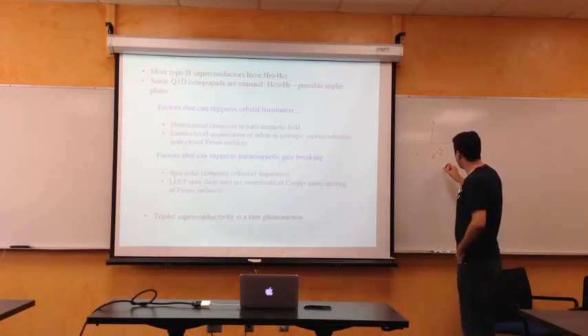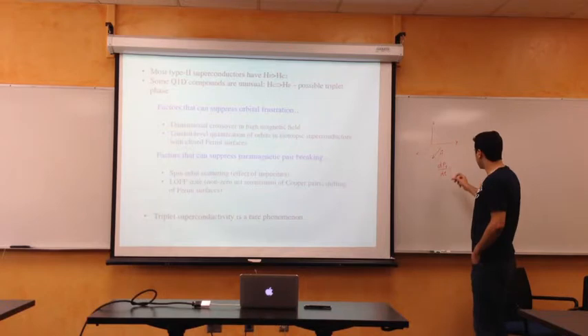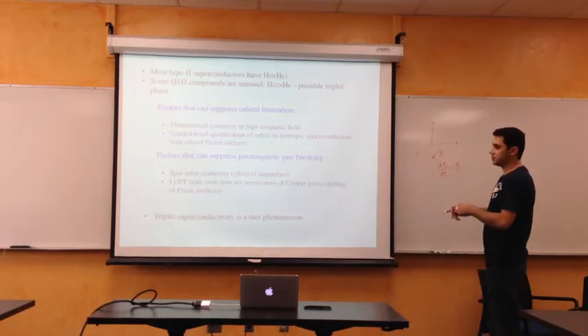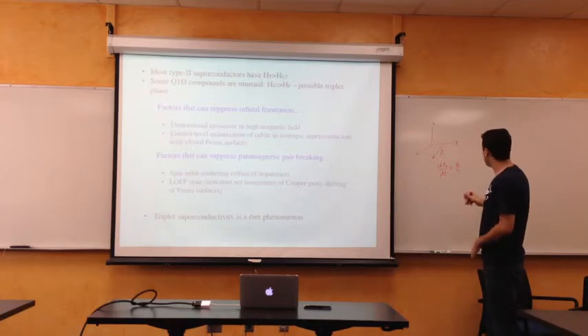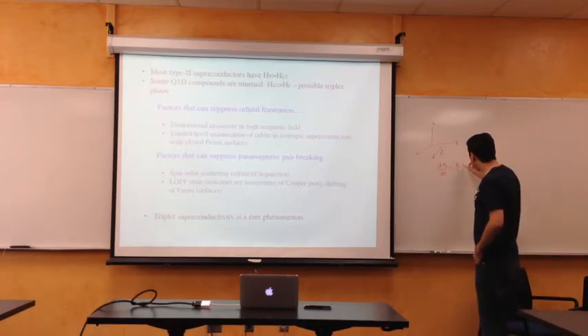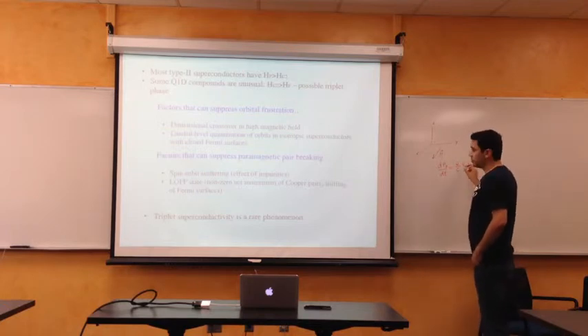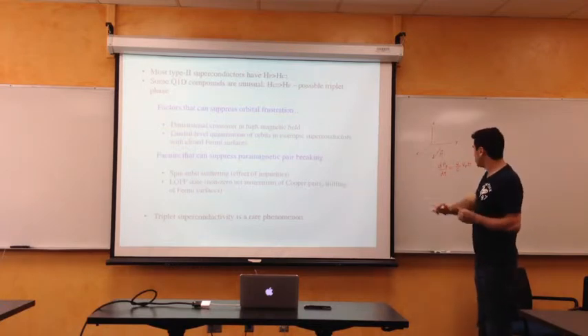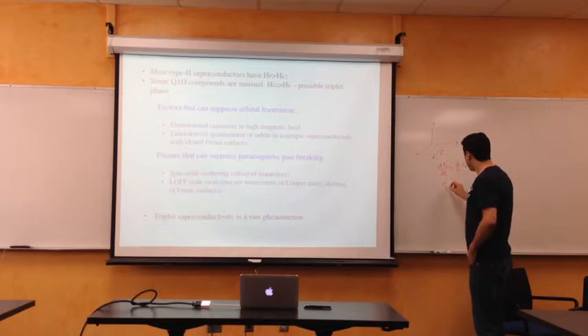So if we write the quasi-classical Newton's law type of equation for the Lorentz force, dp/dt equals v cross H, and v here is just the Fermi velocity. Fermi velocity is approximately constant along the chain, so we have Pz equals E over C times V Fermi H t.